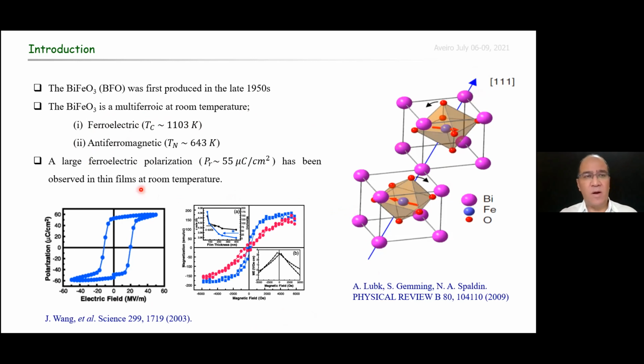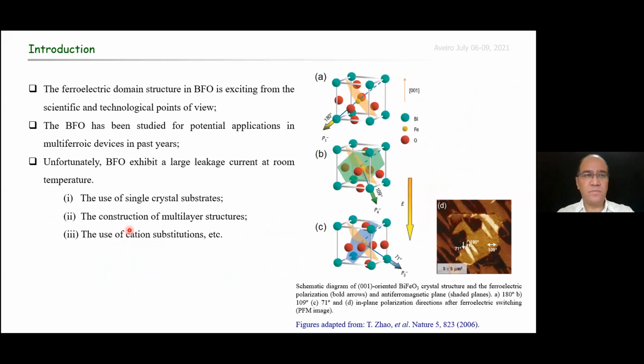BFO is well known for the large ferroelectric polarization observed in thin films at room temperature, as we can see in this ferroelectric hysteresis of an epitaxial BFO thin film. The ferroelectric domain structure in BFO is exciting from the scientific and technological points of view. In this figure, a schematic diagram of the 180°, 109°, and 71° domains is shown in the BFO crystal structure. These domains are indicated in this PFM image. For this and other reasons, BFO has been studied for potential application in multiferroic devices in past years.